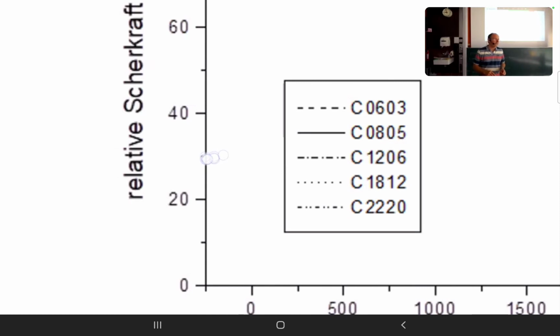Here we take the relative value, because otherwise we would not be able to put it in one graph. For that reason, I have also given the absolute forces at which it breaks. So you can see 2220. That is roughly 1 centimeter square or so, the device. And that has a shear force of 200 Newton. That means 20 kilograms. So it's quite strong, you could say.